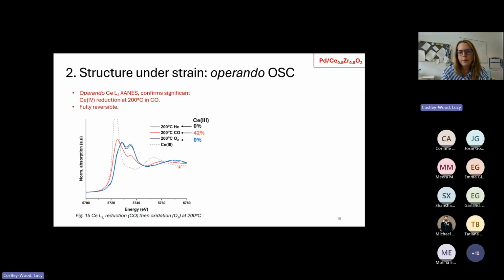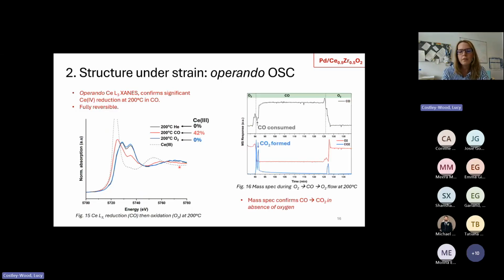We could also confirm this with the mass spec. So when we turn on the CO, we have a small delay in the CO reaching the mass spec because it's being consumed in the conversion to CO2 using lattice oxygen. And we can see this spike in the CO2 here as well. And just to note, again, this is happening in the absence of oxygen. So the oxygen here is coming from the material itself.